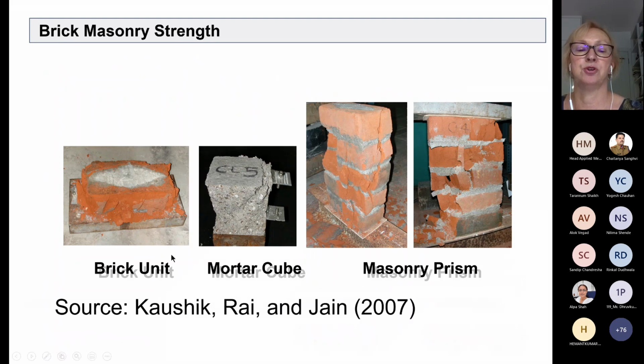Here are some photographs from the paper by Kaushik, Rai, and Jain, which I mentioned and which you have. This is a brick unit. You can see the frog needs to be fully filled before testing. Mortar cube after testing. This is a brick unit after testing. And here are masonry prisms after testing. You can see that this masonry prism has a vertical crack along this shorter side, and you can see that it is crushed. Why a vertical crack?